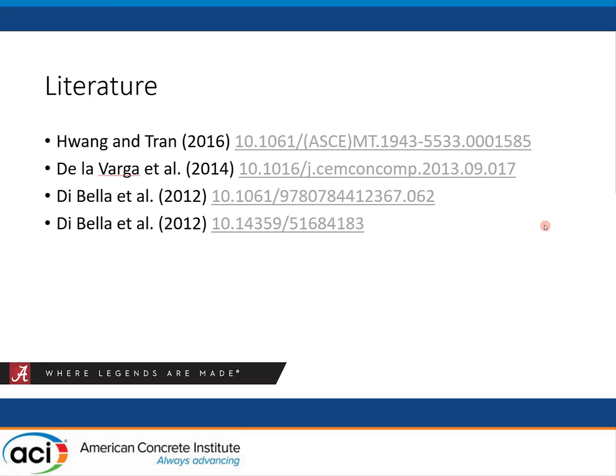And so we had the pieces of this in terms of mixtures, internal curing, and resistivity readings, but nothing tying it together to see, is there an effect? Because if we look at some of these publications, we see that in some cases, through just resistivity readings, there is no difference between an internally cured mixture and its companion normal weight, non-internally cured mixture. And then in other cases, we see a significant difference. And so that's what got me thinking about this.